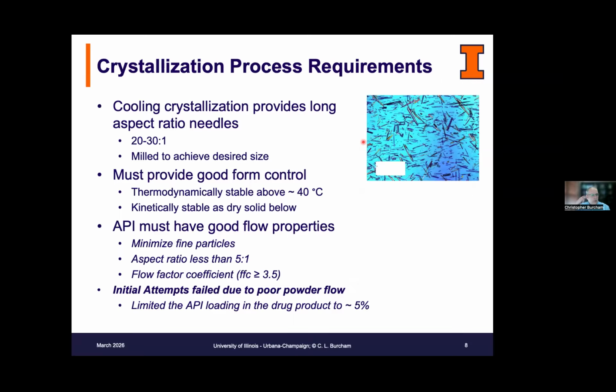So with that in mind, we developed a crystallization process, a very typical cooling crystallization process, where we generated the crystals, we milled them to the desired particle size, we showed the kinetic stability that was needed, but we found after doing this that the initial product that was formed failed in the tablet manufacturing process at high speeds. And this was because there was a large number of fines, as you can see from this photomicrograph. The aspect ratio, while it was much better than in Form 1, was still undesirable.